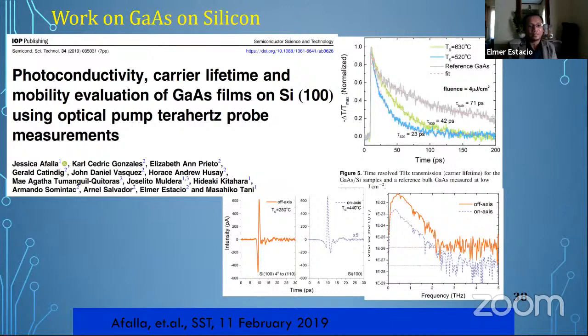And we also looked at trying to survey other ways of doing gallium arsenide films in the molecular beam epitaxy. A while ago, I mentioned that gallium arsenide wafers cost around 500 to 600 US dollars. It's quite cost effective, but still relatively expensive if you compare it with silicon. Silicon is way cheaper. One wafer would cost about a third or a fourth of the gallium arsenide substrate price. And if we are able to successfully grow gallium arsenide on a much cheaper substrate, it should bring down the prices of photoconductive antennas. And that's exactly what we did here.